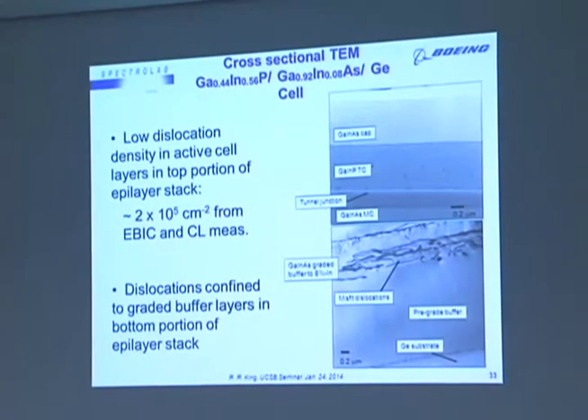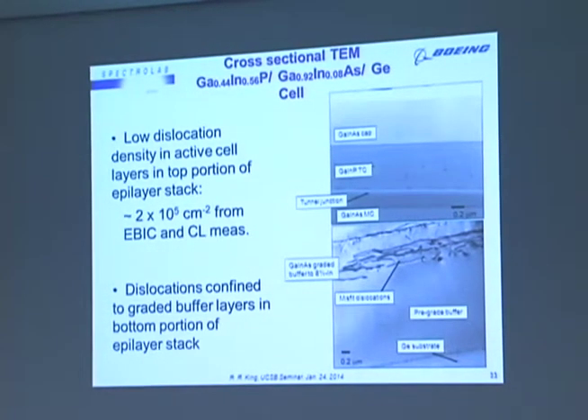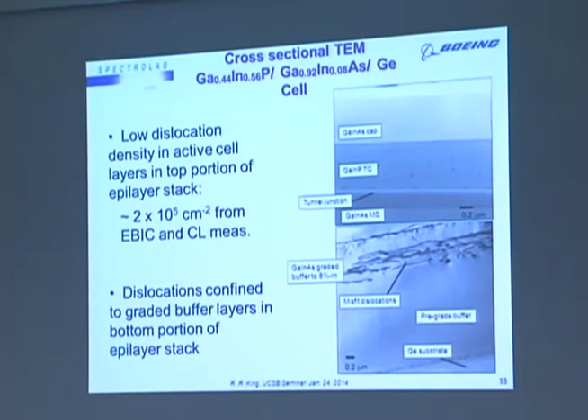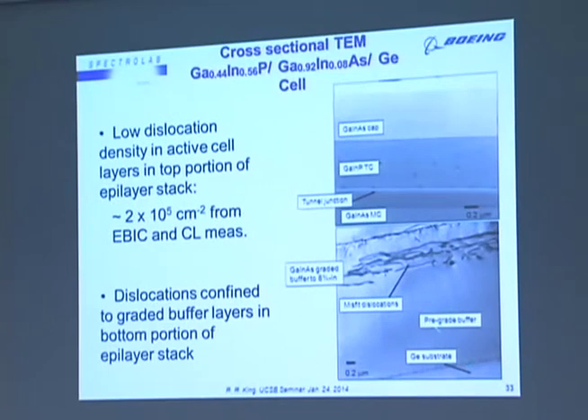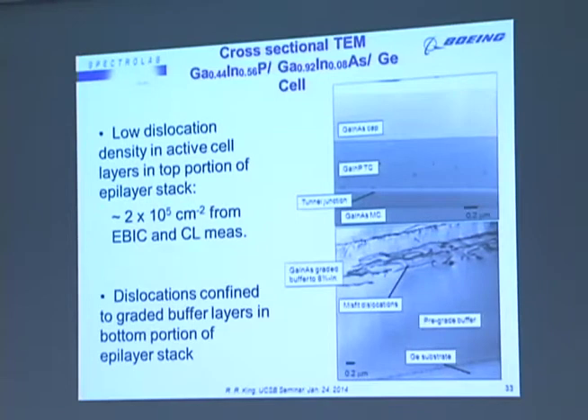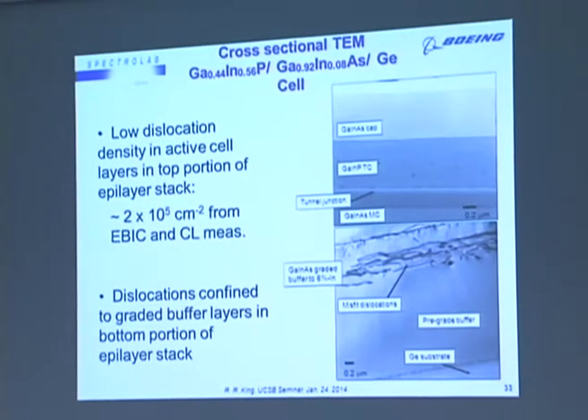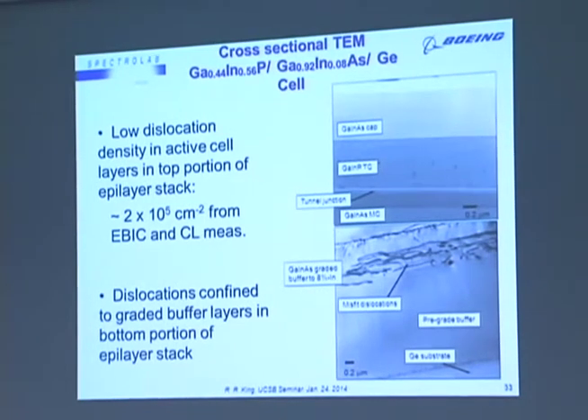So an example of some of those cells, we have cross-sectional TEM of some of those cells here. The germanium substrate is here. We grow a step-graded buffer, and because of the lattice mismatch, there are unavoidable misfit dislocations. But the metamorphic buffer is designed to minimize the threading segments of those dislocations. So we can actually manage to achieve active solar cell layers up here in the active gallium phosphide and gallium arsenide solar cells that have remarkably low 2 times 10 to the 5 per square centimeter dislocation densities.